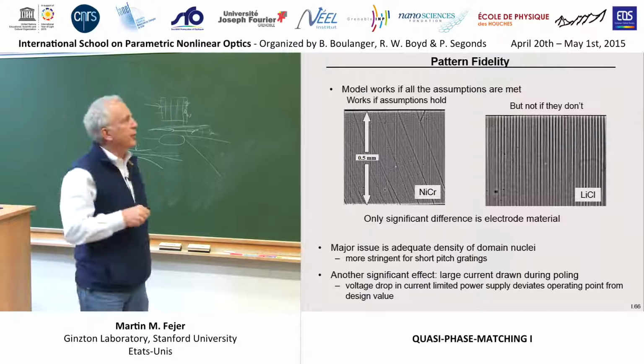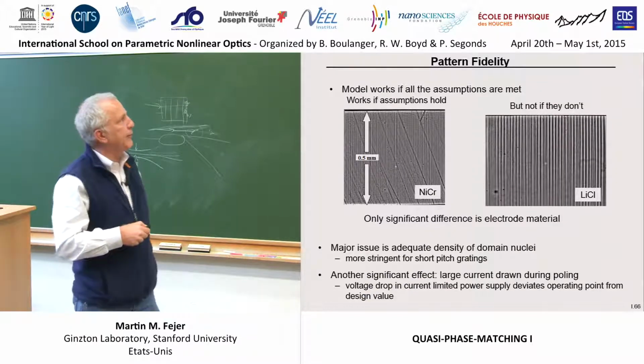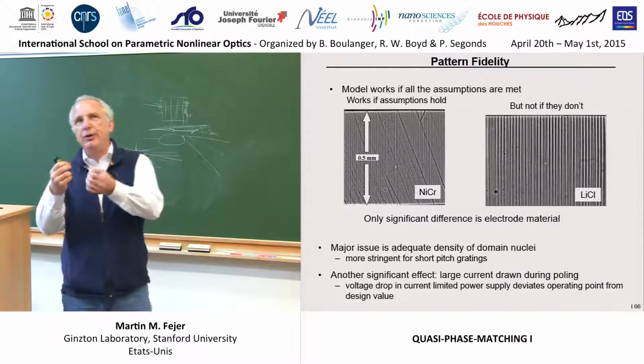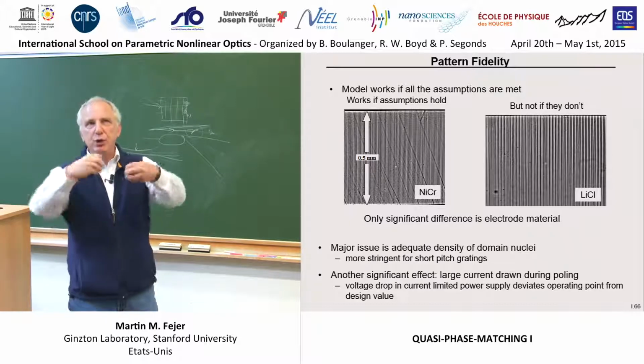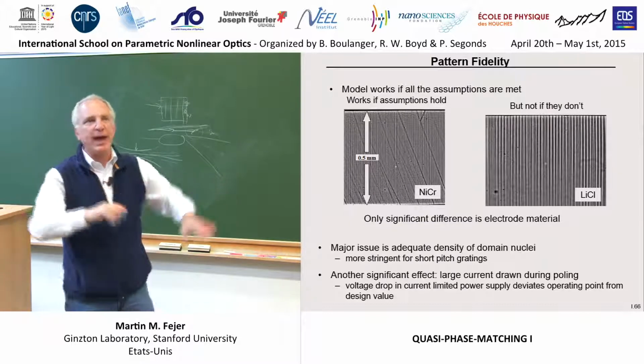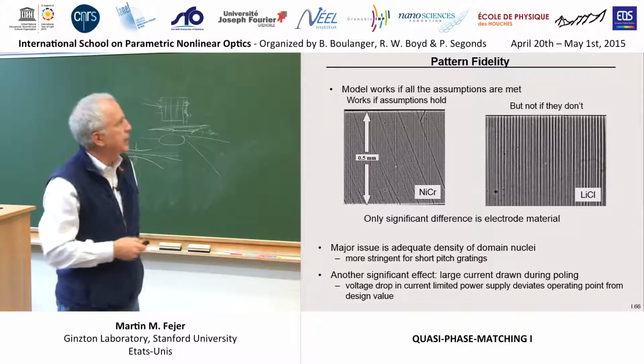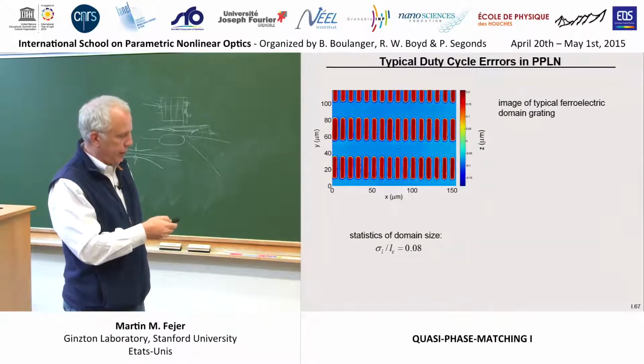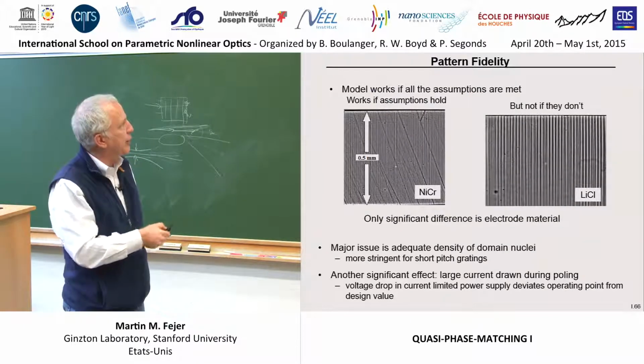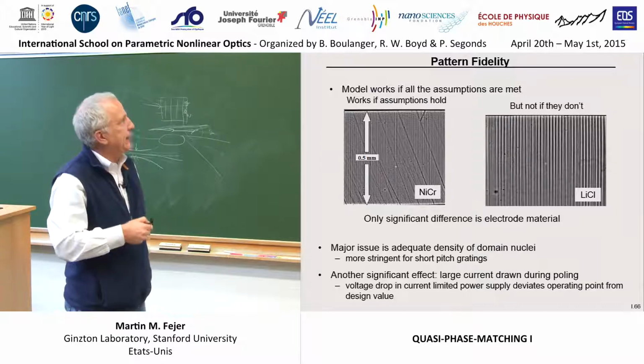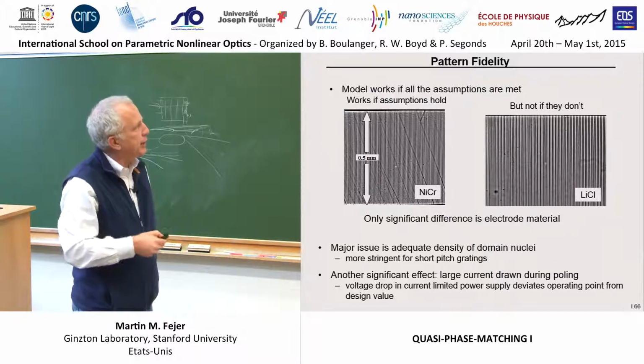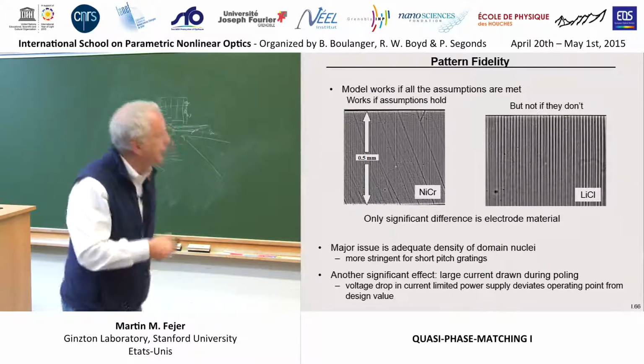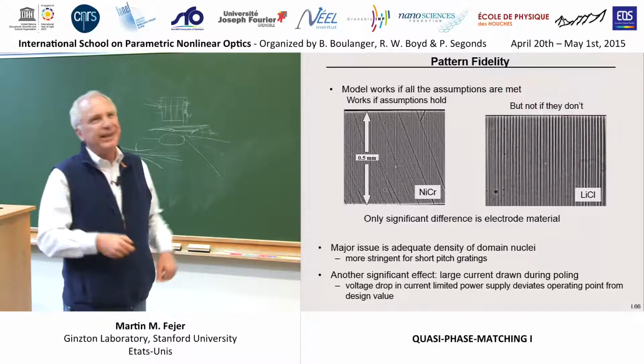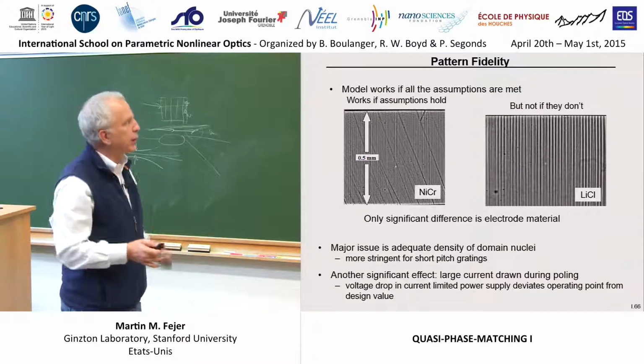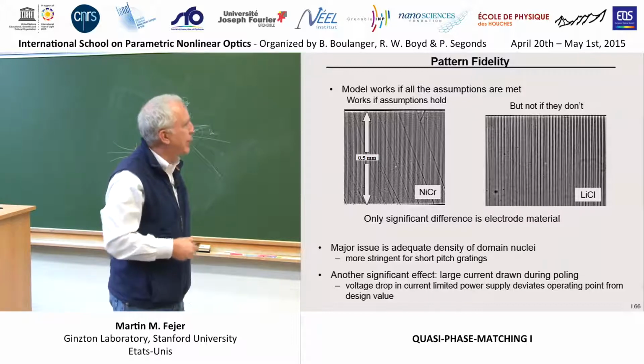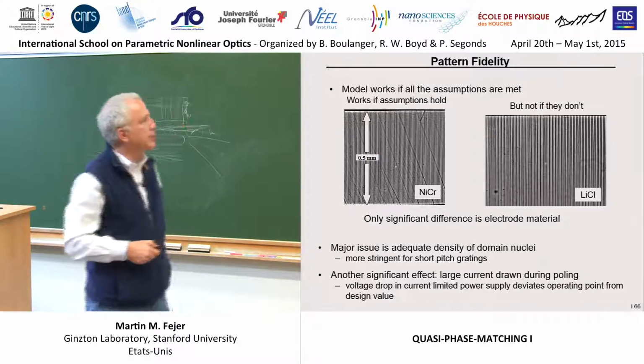Everything gets more difficult as the periods get finer. You have to have better control over everything. You need a higher density of nuclei to get the behavior to average properly over the whole wafer. There's a greater tendency for the domains to pinch off as they go through the thickness. In addition to becoming more difficult as the period gets shorter, it gets more difficult as the sample gets thicker. The physics of that is a little murkier. I can't say I fully understand why there's such a strong dependence on thickness, but there is.